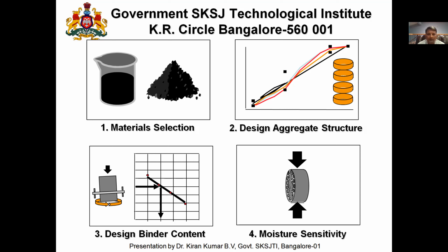about the Marshall method, the Marshall method gives blows onto the aggregate structure which is carefully chosen in the second step, with a certain binder content or a trial binder content to start with. After giving 150 blows, 75 on either side, on a cylindrical specimen of about 100 mm diameter and 63.5 mm height, we check its volumetric properties and its stability after soaking it at 60 degrees centigrade, as well as the resistance to deformation and the flow, basically how the material starts crumbling or crushing when the load is applied constantly. Based on these parameters, we fix the binder content.